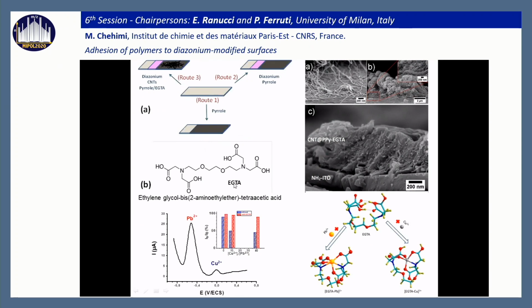By DFT, we have shown that the stability of the polypyrrole EGTA lead complex was stronger because the EGTA is hexa-coordinated with lead compared to the penta-coordination with copper.